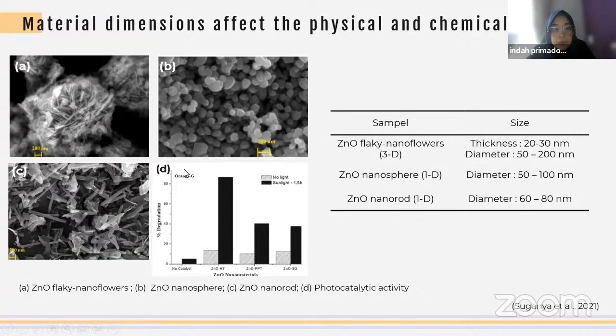You can also see here that when we use nanospheres compared with nanoflowers or nanorods, the zinc oxide flaky nanoflower gives the highest percent degradation compared with the zinc oxide nanosphere and zinc oxide nanorod. Although the diameter of the zinc oxide nanorod and nanosphere is smaller than the zinc oxide flaky nanoflowers, in this paper they said the exposed active site of the flaky nanoflower is bigger than the others.